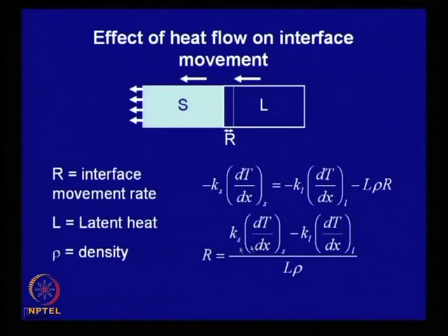This expression gives you a heat balance, meaning how the heat is extracted from this liquid so that it solidifies, and here there will be some amount of latent heat which will come out, and that latent heat also has to be extracted, and the only direction it can flow through is this. Now, there are 2 important things. One, of course, is the cooling rate or the rate of heat extraction through conduction through solid, through the liquid layer, the boundary layer that forms, and it also depends on the rate at which this interface moves. But often these two, the heat extraction and the movement of this interface, are related, they are not independently controllable.